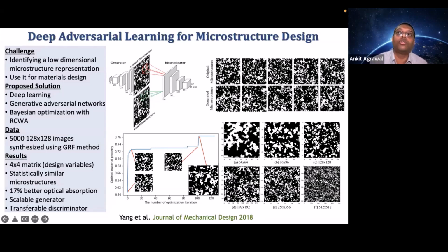Not just visually, but also in terms of statistical correlation and lineal path correlation, 2-point correlation, all kinds of tests we did to see that these are really statistically similar. And then when we combine that with the Bayesian optimization loop, we could use it for inverse design. So once we have an ability to generate a microstructure, we can now optimize the property. And here you can see in just about 100 iterations, we could get to this optimal property, which in this case was optical absorption, and 17% better properties than what have been observed before using other optimization methods.